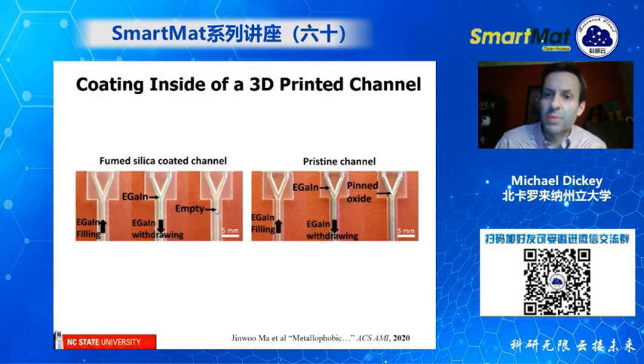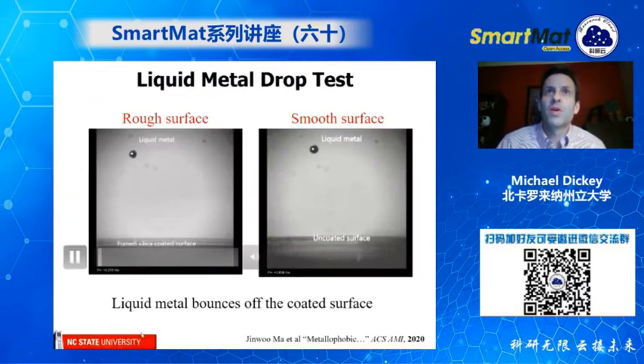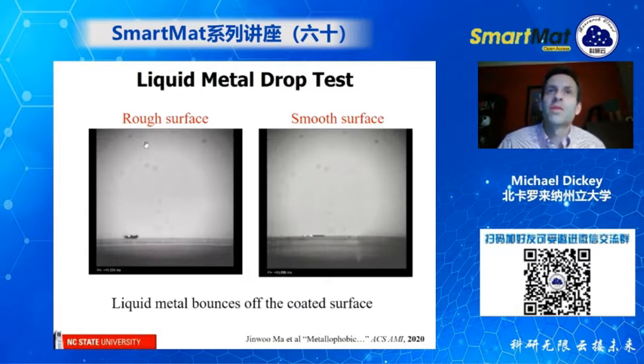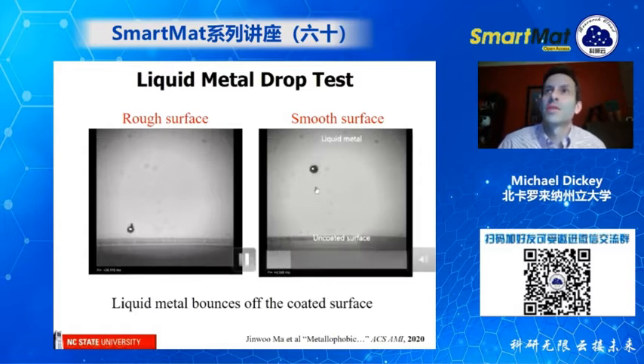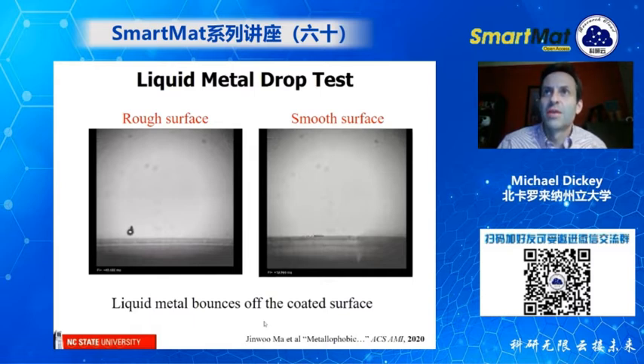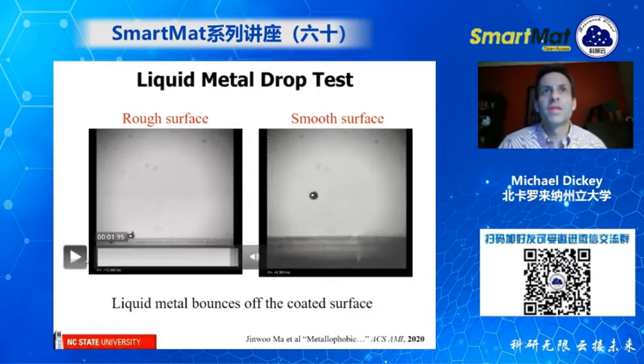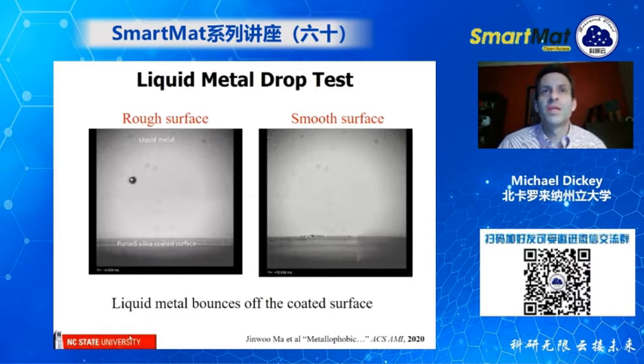So then we did another experiment where we dropped liquid metal droplets and we used a high-speed camera. And on the left, you can see on these rough surfaces, the droplet will actually bounce. On the right-hand side, when it's on a smooth surface, the droplet will come down and it will stick because of the oxide layer. In fact, you can see that it stays flattened. So the key idea here is that these rough surfaces will prevent adhesion.